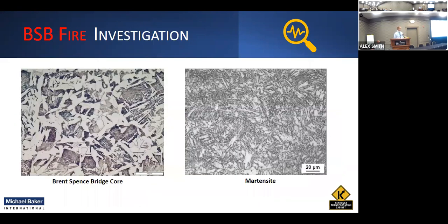The next thing they were looking at, they put it under a microscope. The picture on the left here is a picture of the crystalline structure of the steel from that particular sample. And what you'll notice there is that in general, it's kind of globular, if you will. The specks are still round and square, and that's kind of the steel section. The formation of martensite, when you elevate it and actually quench steel, the crystalline structure of the steel changes, and it looks more like you see on the right side. It looks more fractured, more like needles.